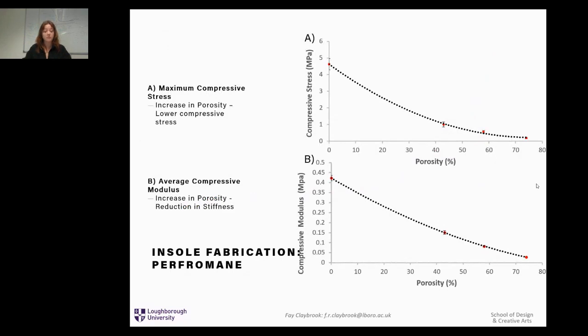So what I found was that there was a clear correlation between the porosity and the maximum compressive stress, whereby with increased porosity, there was a lower measured maximum compressive stress. This was also reflected in the calculations for the compressive modulus, the Young's modulus, which imply a reduction in stiffness for increased porosity. It was noted that the calculated error was higher for the structures with increased porosity, for both maximum compressive stress and the compressive modulus.